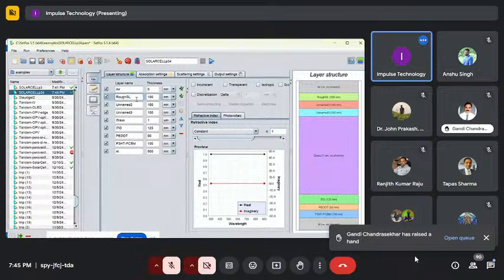Rough glass 1, rough glass 2. For the rough interfaces, as we know, they enhance the transmission of the light waves through the interface. We try to apply this concept because we decrease the reflectance at the outer air-glass interface and make the transmission from glass to ITO as advantageous as possible.